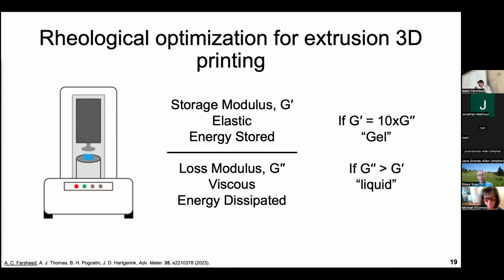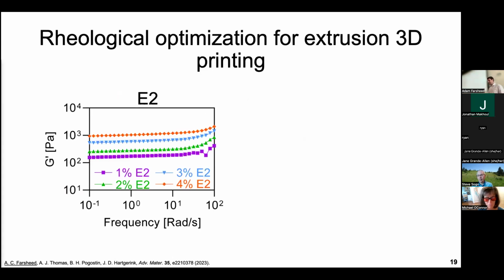And so to orient us to the data that I'm about to show, if the storage modulus, the G prime as we call it, is around 10 times the G double prime, then we have a gel. But if the G double prime is larger than the G prime, we have a liquid. And so the first thing that I did that blew my mind, that not many people had tried before in our lab, but I took one of our materials, E2, and I just said, what happens if we keep adding more and more material to our system? So just very briefly, the way that we make these hydrogels from 1 to 4% is we take 1% our material, 99% HBSS buffer, or you can think of it as similar to water, but with a little bit of physiological salt added.